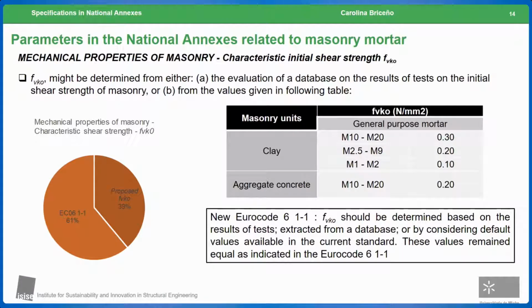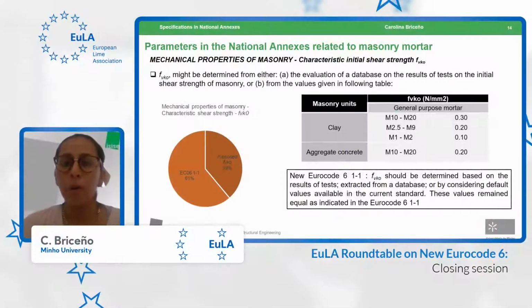Another parameter that is discussed is the characteristic initial shear strength. According to the 1995 version as well as the 2018 version, this strength could be determined based on the evaluation of a database of the results of tests or from the values given in the table. 61% of the countries consider the table indicated in the standard. Meanwhile, 39% of the countries consider or propose a particular initial shear strength. However, the criteria and also the values are very similar to the ones shown in the standard, with some exceptions, as for instance in the case of Norway, where the values are lower than the ones indicated in the standard.